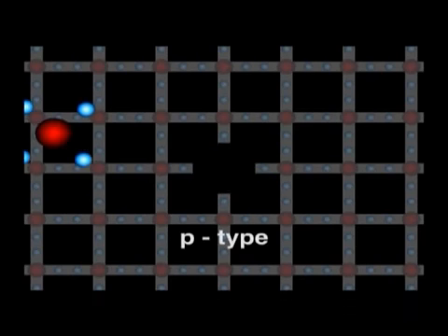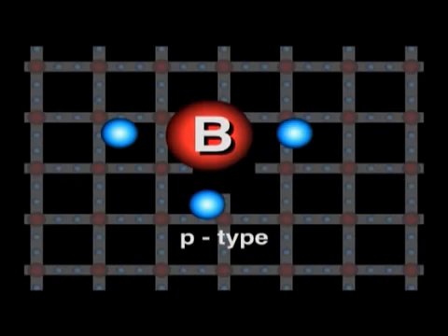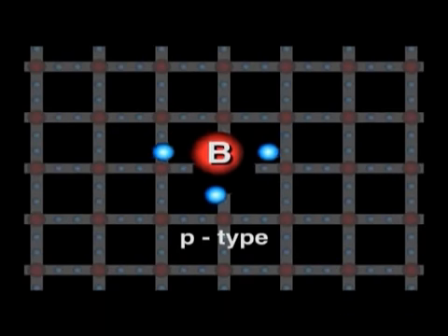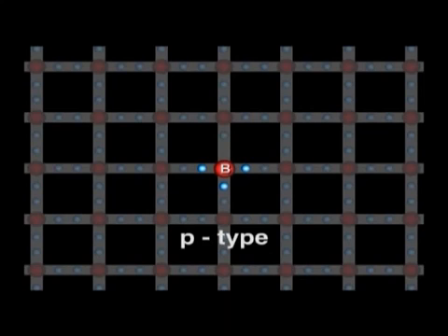One can make p-type silicon by adding impurities, such as boron, with only 3 valence electrons. It forms only 3 complete bonds with the neighboring silicon atoms, leaving 1 incomplete. This incomplete bond has the ability to capture an electron, usually a nearby electron from the valence band. This neighboring electron leaves behind a positive hole that can diffuse through the crystal at ordinary temperatures.